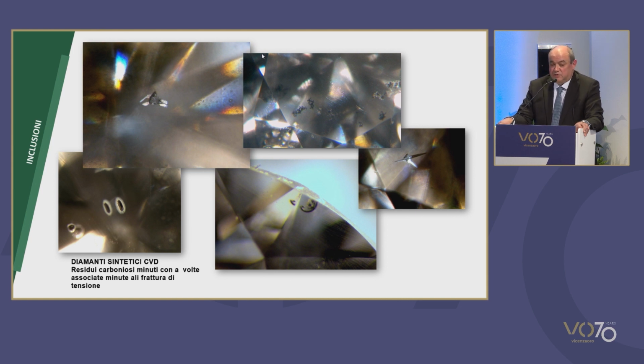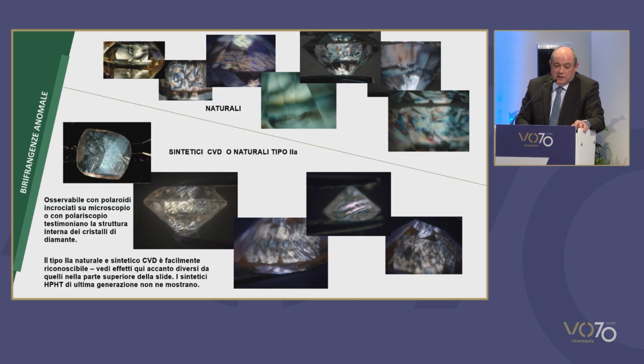And CVD diamonds can be more difficult to identify. There are very few small inclusions with this shape, because in fact they are carbon residues, a carbon which has not crystallized. We are halfway between diamond and graphite, something amorphous, with some holes around. It's pretty difficult to see them, also for us. So it's not so easy to distinguish them from natural inclusions. Well, this can be very useful. But you have to have specific instruments.